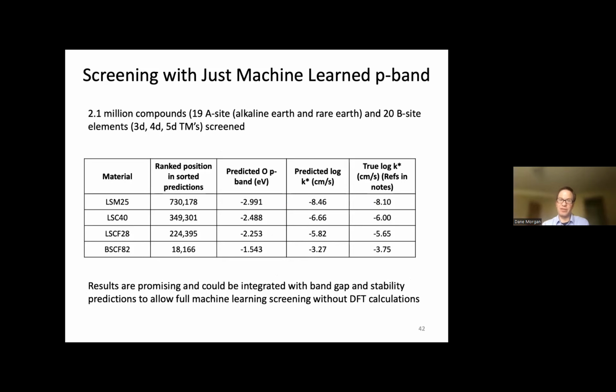So we did that. We screened 2.1 million perovskites, which was kind of all the ones we thought were potentially interesting in terms of the types of elements they had. We looked at 19 A-site elements and about 20 B-site elements, built a grid of compositions, screened 2.1 million compounds, and found that we could get reasonable predictions on surface exchange coefficients as far as we can tell. Here are 3 or 4 known materials. We looked at their ranking. They go from about 730,000 to about rank 18,000 in the 2.1 million. And we predicted their surface exchange coefficients, and they fall typically within about half a log unit or a little bit more of the known experimental values.